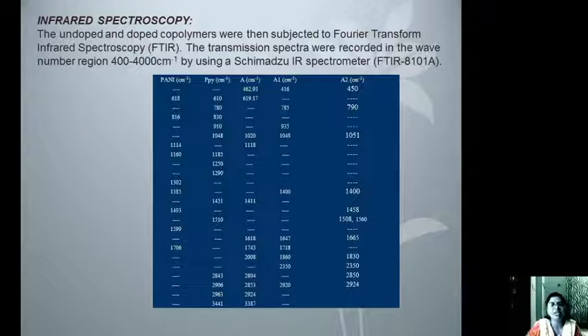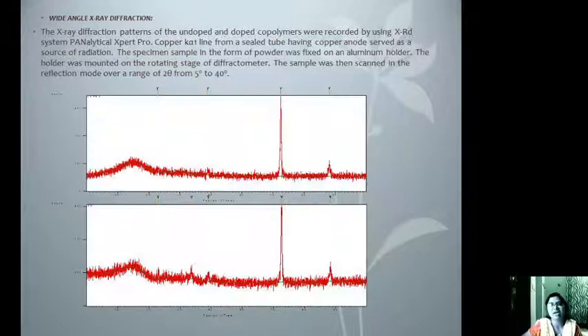From the table it is clear that several band positions of the monomers, that is the homopolymers, are missing in the copolymer, which are again missing in the doped copolymer. This proves the influence of the dopant on the basic copolymer chain. Due to the hetero linkages, some of the bonds are getting twisted and some polar effects are observed, because of which the shifting and arising of new bands is seen.